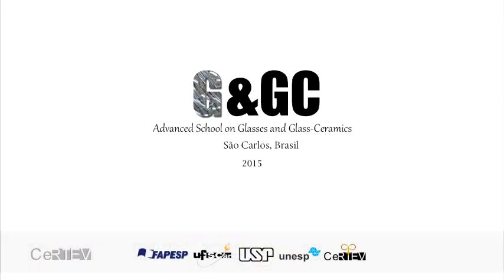And now I shall tell you something about mixed network former glasses, because when the glass formers are changing but the charge carrier concentration is kept fixed, still there is an increase or decrease in conductivity, and this is called the mixed network former effect. Here we can see the silver borophosphate glass, with boron oxide and phosphorus oxide. We are replacing phosphorus oxide by boron oxide, and also we are changing the silver ion content.